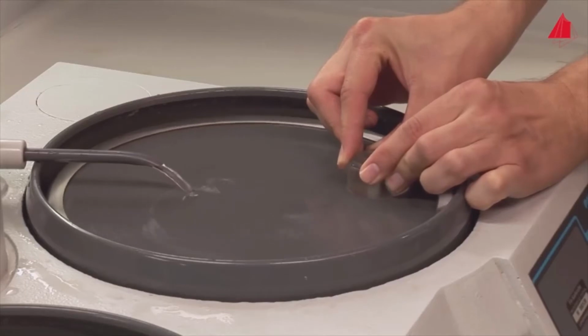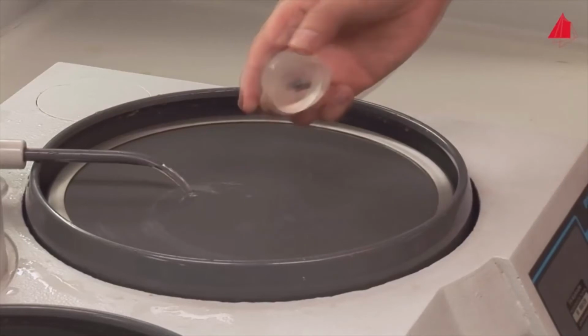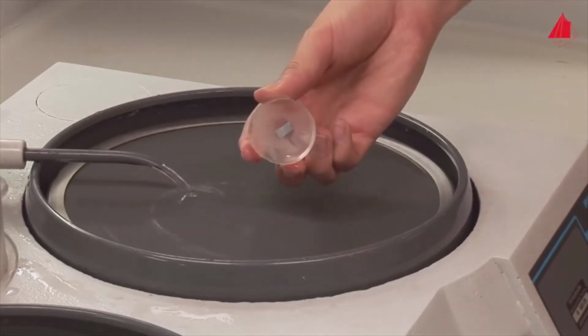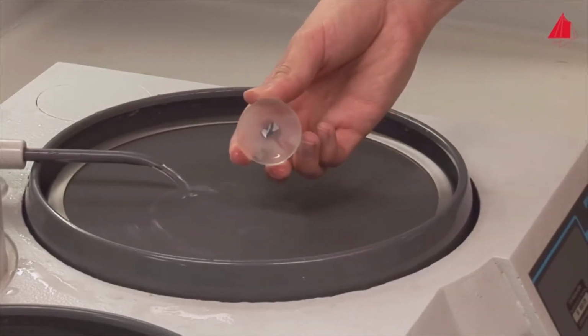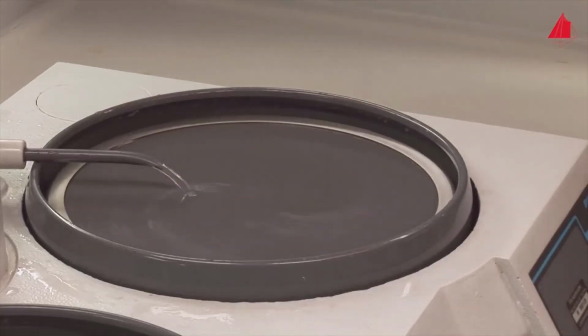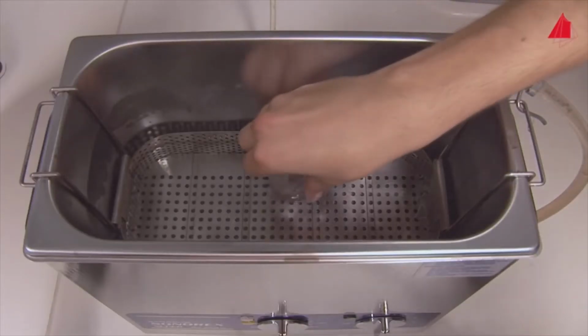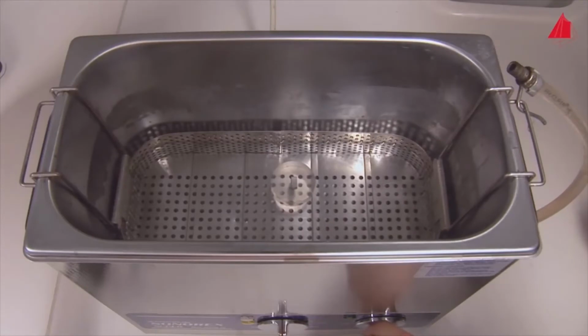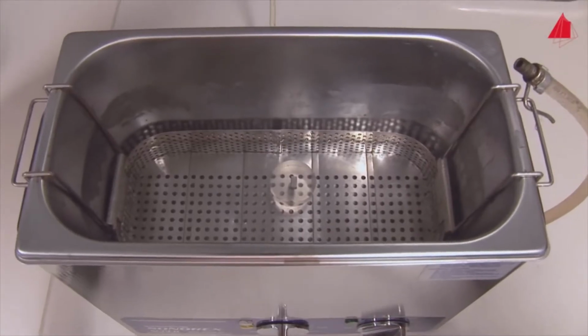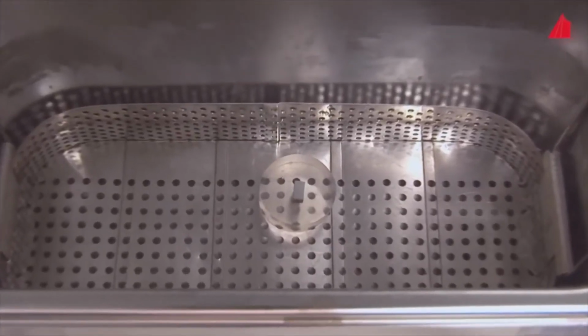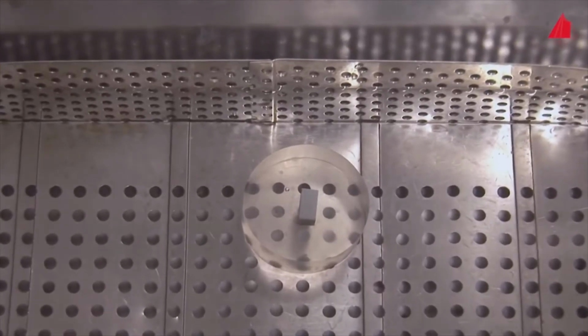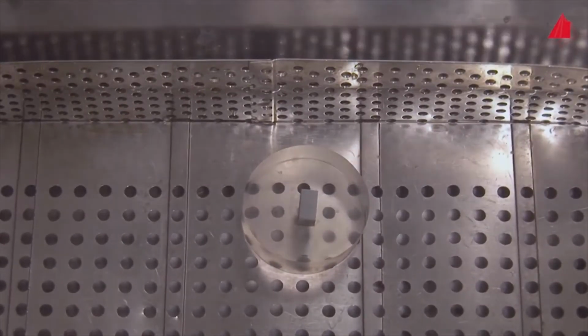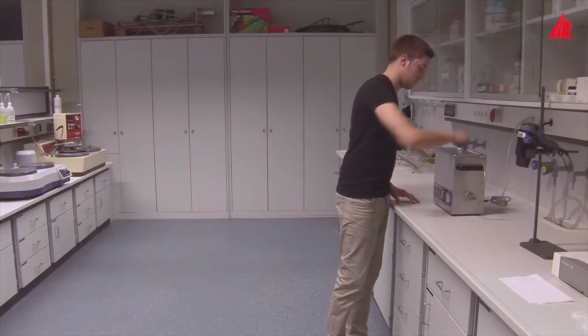Grinding continues with 600 grit and 1000 grit abrasive paper until an immaculate, finely ground specimen has been achieved. The specimen is now ready for polishing. An absolute prerequisite for polishing is a thoroughly clean specimen. The ultrasonic bath and running water help to remove any residue from the ground surface. Otherwise, hard particles might be pressed into the polishing cloth and scratch the surface.